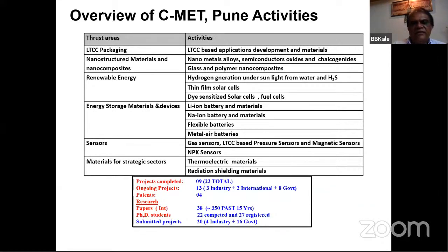Then materials for strategic sectors, such as thermoelectric materials. For example, in our nuclear reactor systems, the outer temperature may be some 800 to 900 degrees centigrade. Using this heat, can we generate electricity? Thermoelectric material will be a good material. It has the Peltier effect and the Seebeck effect. Through the Seebeck effect, we can generate electricity, and with the Peltier effect, when we apply a little voltage to these materials, we get cooling properties.